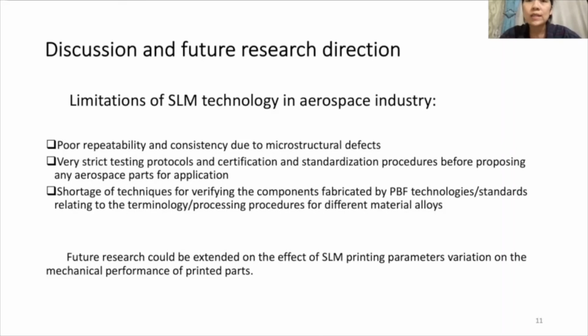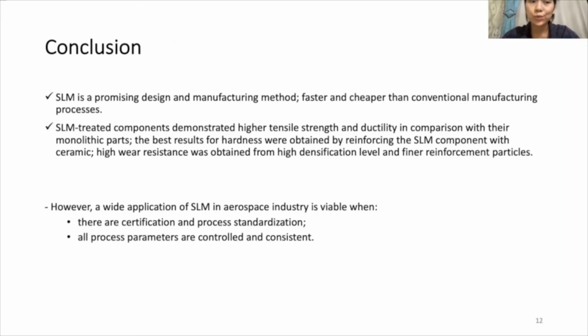Future research would be extended on the effect of selective laser melting printing parameter variation on the mechanical performance of printed parts. There are more than 100 selective laser melting process parameters, but the key parameters are those which significantly influence the density of produced parts. They are layer thickness, hatch spacing, and laser power. As the laser is an important component of the selective laser melting process, the choice of the laser source is vital due to the different energy absorption parameters. The variation of laser parameters is very important in standardization and enhancing repeatability and consistency. So let me conclude my presentation.